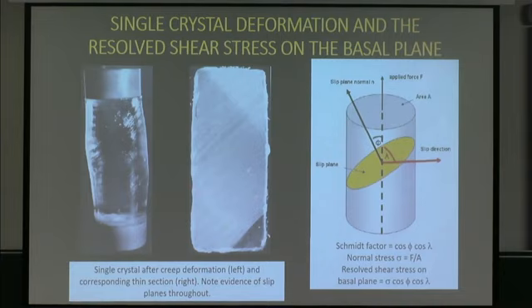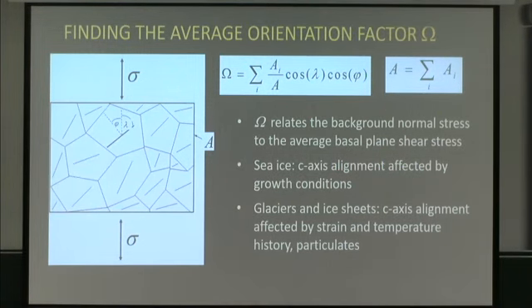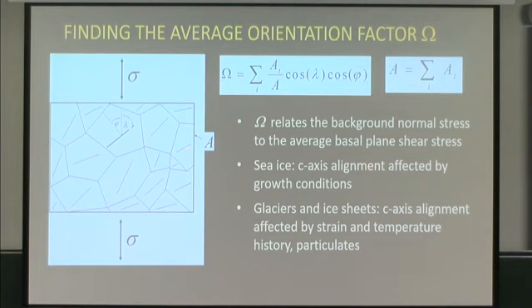This is a polarized thin section. You don't see any color because of the orientation, but you do get a sense of all these slip lines which are generated by dislocations on these basal planes. The model will use an orientation factor, omega, which is basically a Schmidt factor, which converts an axial stress to a shear stress on a given basal plane. When we have a polycrystal, each crystal has its own orientation, which can be determined by observation, and then we just calculate the average shear factor for the whole polycrystal, and that gives us a quantity we use to describe the fabric. So that's one of the real important physical characteristics of sea ice.